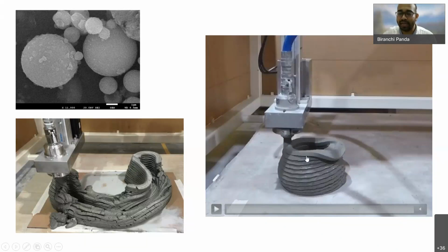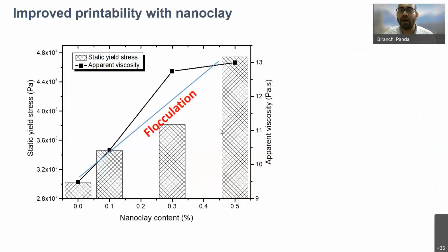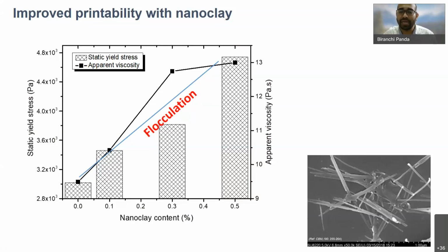We call this buildability: how many layers you can deposit. We wanted to improve the buildability of this material, and for that we use some nano clay. This nano clay really helped in improving the yield stress. As you can see, with 0% dosage the yield stress is very low, but when the dosage increases up to 0.5%, the yield stress significantly increased. And if you look into the mechanism of how the clay is affecting the process, we found flocculation, which is again improving the yield stress of this waste replaced material.